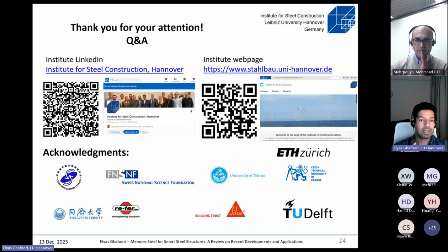Fatigue, creep, relaxation, corrosion, galvanic. We have different types of corrosion: galvanic corrosion, also normal corrosion, stress corrosion. We have done research on nearly all of them. In our fatigue test that I actually did myself, we have 2 papers on fatigue of iron-based shape memory alloy.